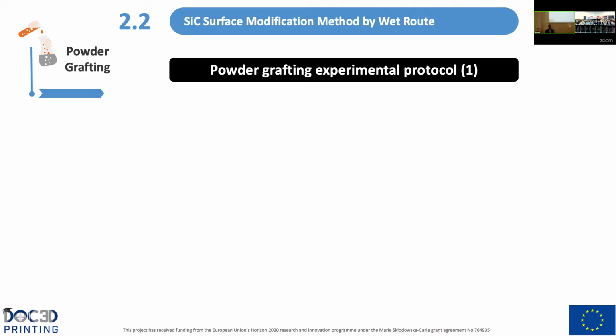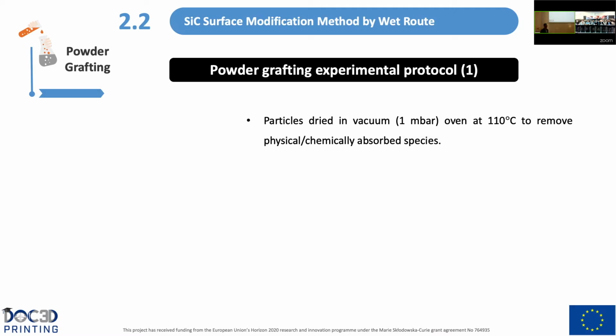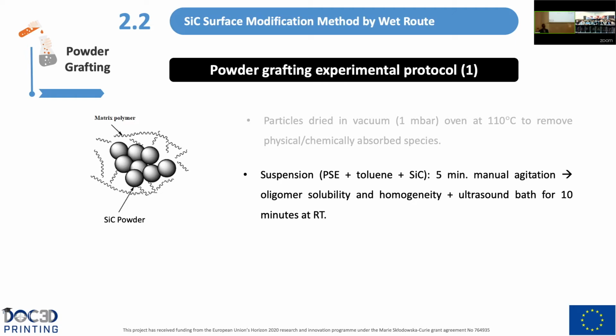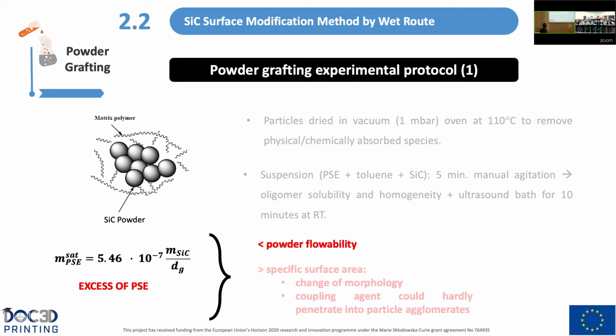So now regarding the powder grafting experimental protocol, by reviewing the literature, we use the following protocol. Firstly, the particles are dried in a vacuum oven at 110 degrees to remove physically and chemically adsorbed species. Then this suspension of polycarbosilane, toluene, and silicon carbide is subjected to 5 minutes of manual agitation to improve the oligomer solubility and homogeneity, and it's subjected as well to an ultrasound bath for 10 minutes at room temperature. And regarding the expression of mass, it's very important not to use an excess of polycarbosilane during the process. Why? Because this could decrease the powder flowability, so we wouldn't be able to use this ceramic powder in an additive manufacturing process such as powder bed selective processing. And moreover, this could increase the specific surface area, producing a change in the morphology, and the coupling agent would hardly penetrate into particle agglomerates.